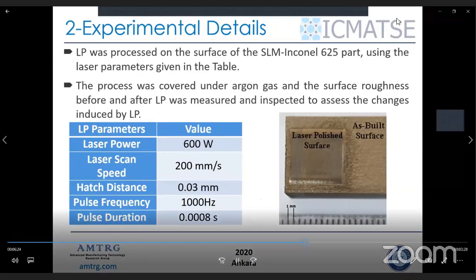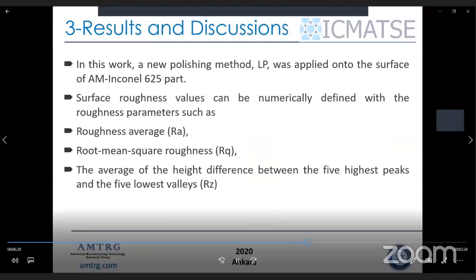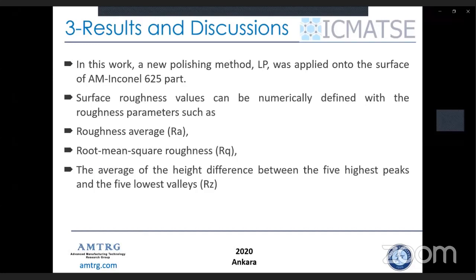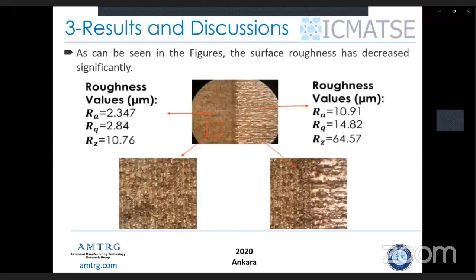In this work, a new polishing method, laser polishing, was applied onto the surface of additive manufacturing Inconel 625 part. Surface roughness values can be numerically defined with the roughness parameters such as roughness average RA, root mean square roughness RQ, the average of the height difference between the 5 highest peaks and the 5 lowest valleys RZ. As can be seen in the figures, the surface roughness has decreased significantly. The right side of the figures represent the as-built surface, while the left side represents the laser polished surface.